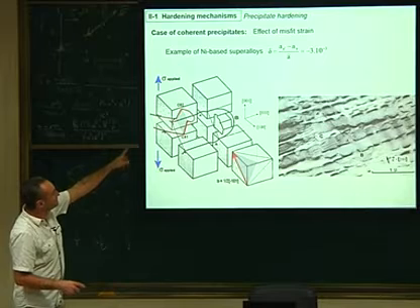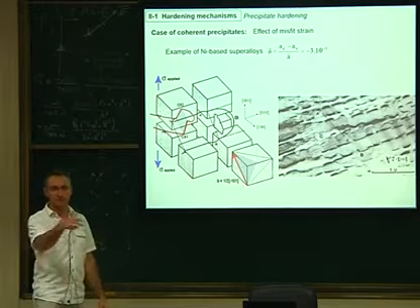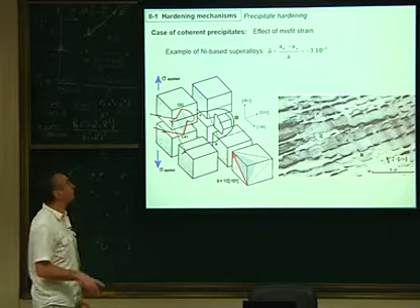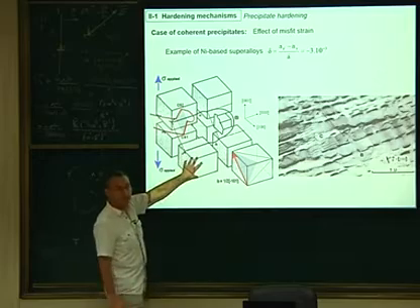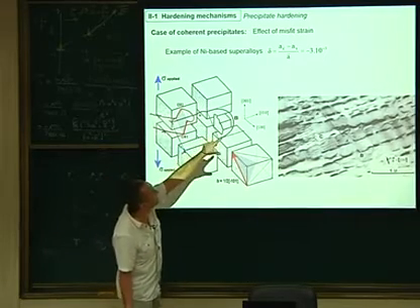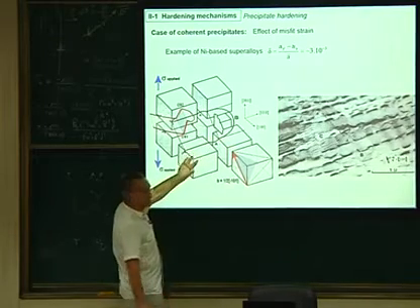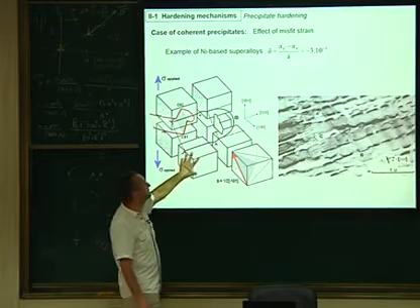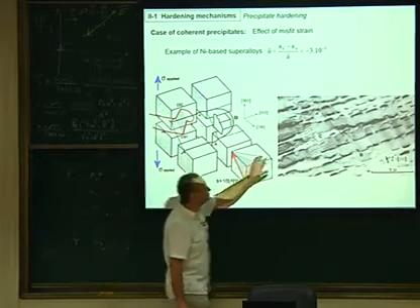Now the second one is the misfit strain, as I explained before, and a good example of that is the superalloys. I know that some of you are working on superalloys. So superalloys are typically nickel-based superalloys, where you have a gamma prime precipitate, which is usually smaller in size than the matrix. So the gamma prime minus gamma over the average gamma is -3, 10^-3. So there is a slight shrinkage of the matrix. It's coherent particles, so they are exactly the same network, but they are smaller. And how dislocations behave in these superalloys depends very much on that misfit stress.